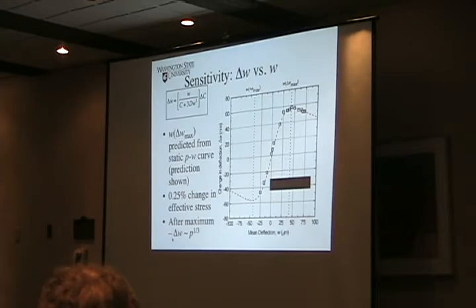Let me jump to the next slide, which should have, no, I still did it wrong. I apologize for this. What we end up finding is that since there's better piezoelectric coupling as strain increases, you end up with a more effective sensor or actuator as you increase the strain, which is kind of counterintuitive. You usually would think that you get a larger throw if you didn't pressurize the membrane as much, but you're getting better electromechanical coupling once it's in the 3-1 mode rather than a bending mode. So when you have a membrane, treat it like a membrane instead of like a cantilever, bulge it out, and it turns out it actually performs better at large deflections. You get a maximum sensitivity to this device.